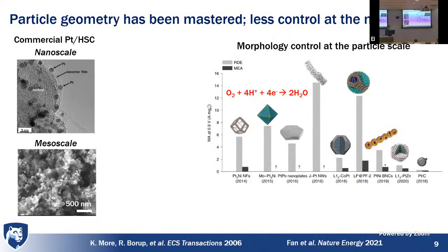And so the playbook largely has been, we just need some fancy new nanoparticles, like we have a core particle and then a monolayer of platinum coated on it. And we would get to these ultra low loadings, and this would solve all our problems. So in our commercial catalysts, we tend to have these platinum nanoparticles, fuel cell catalysts, decorated on high surface area carbon. That's here. We can do a rotating disc electrode experiment in the lab.